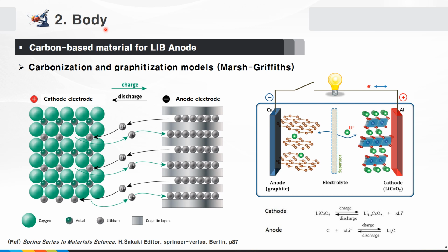The charge and discharge reactions at the carbon anode used in the LIB are as follows. During the charge reaction, the carbon material undergoes a reduction reaction in which lithium ions are intercalated into the carbon materials, and a lithium-carbon compound is formed. During the discharge reaction, oxidation occurs and lithium ions are deintercalated from the carbon materials. As a result, the anode stores the lithium ion during the charging process and releases the lithium ion during the discharging process. Therefore, the anode material greatly affects the basic performance characteristics of the secondary batteries, for example, capacity, power, and life characteristics.